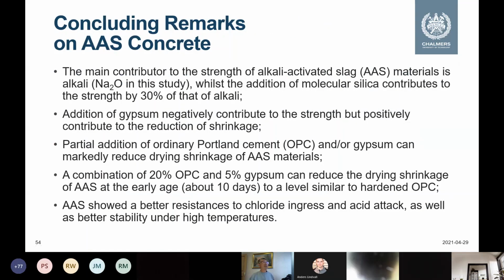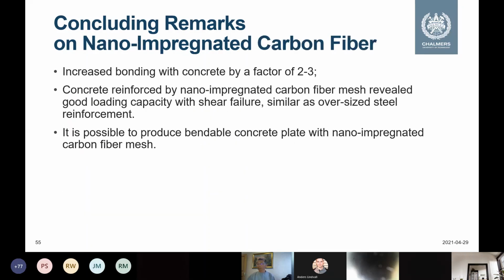So with alkali-activated concrete, it can keep similar strength to ordinary concrete, but shows better resistance to chloride ingress and acid attack, and also better stability under high temperature. For nano impregnated carbon fiber, we can see that it increased the bonding with concrete by a factor of 2 or 3 times. The concrete reinforced by nano impregnated carbon fiber mesh shows very good loading capacity with shear failure, very similar to oversized steel reinforcement. So it is possible to produce bendable concrete plates with nano impregnated carbon fiber mesh.